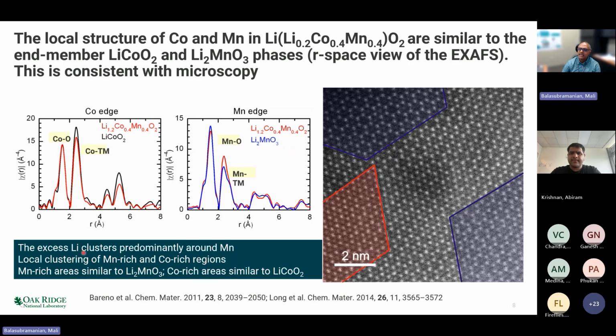And so manganese-rich areas are similar to Li2MnO3 and the cobalt-rich regions are similar to lithium cobalt oxide. So on a local scale, this material looks very different than what is expected purely on the basis of a randomly distributed solid solution.